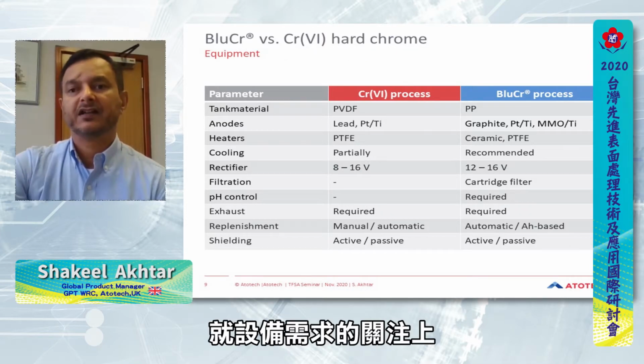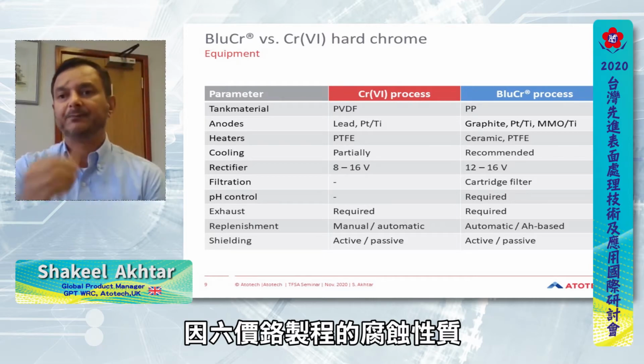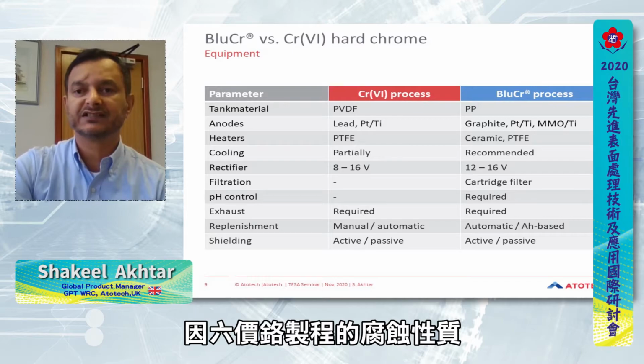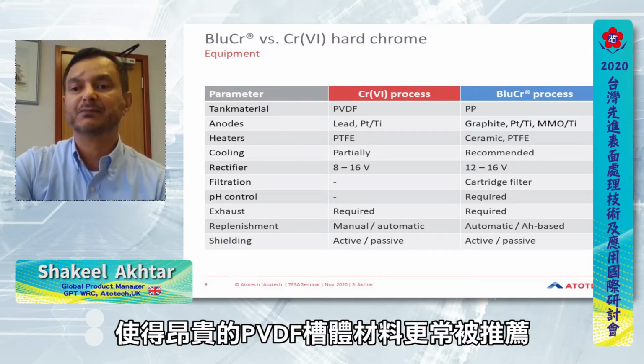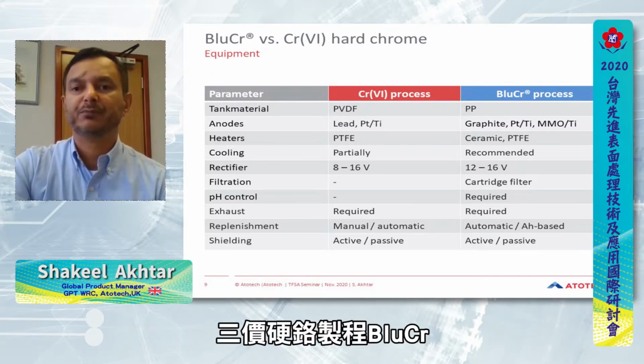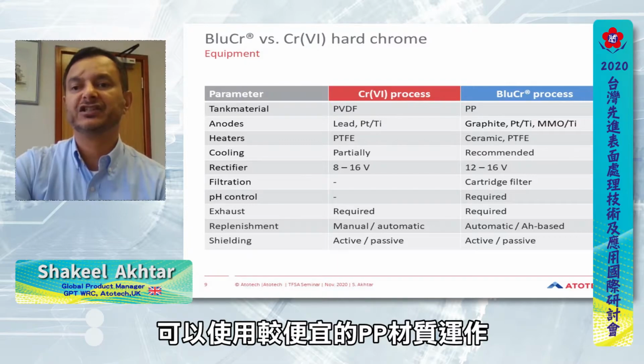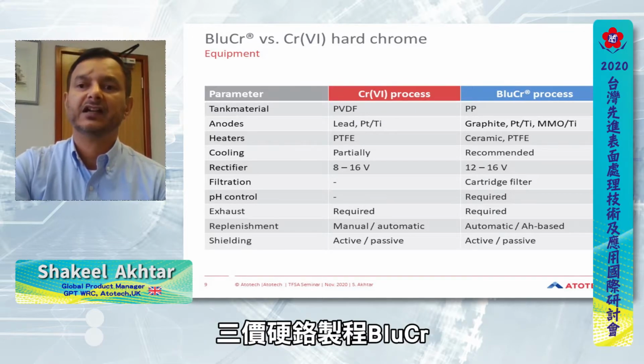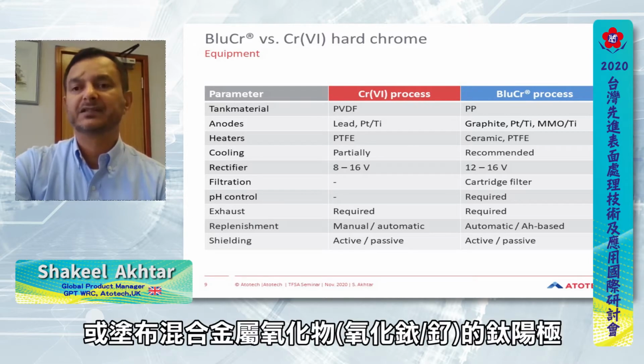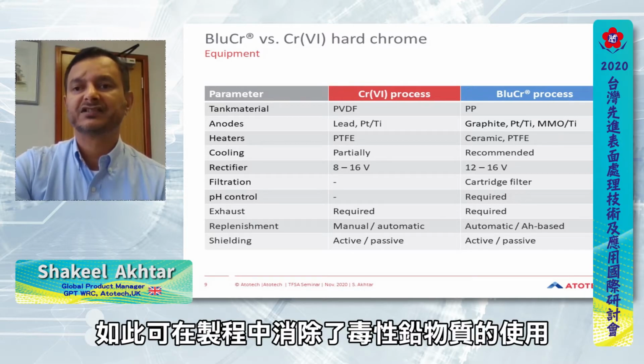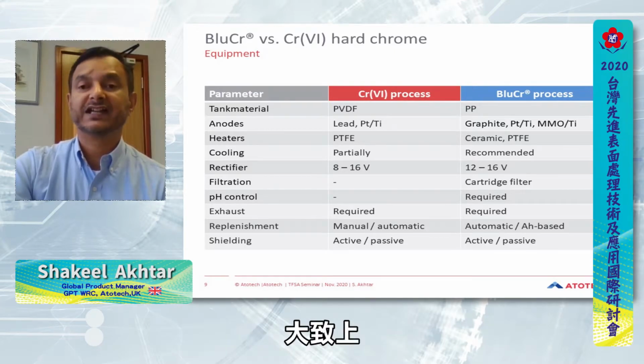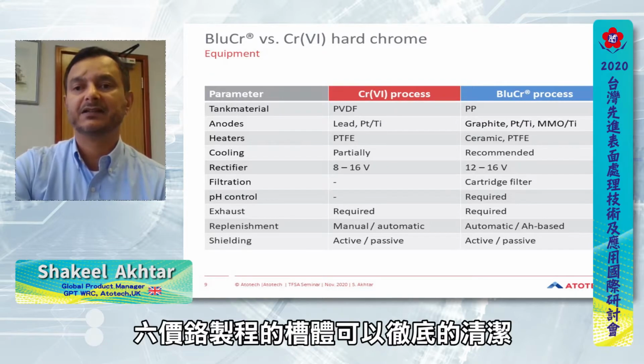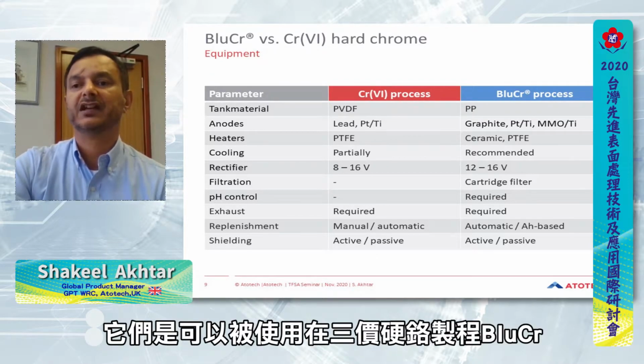As far as equipment requirements are concerned, due to the corrosive nature of hexavalent chrome processes, expensive PVDF tank material is usually recommended. However, the blue chrome process can be operated in tanks constructed from cheaper polypropylene materials. Blue chrome can be operated with graphite, platinized titanium, or mixed metal oxide on titanium anodes. Thus, the elimination of toxic lead from the process with blue chrome. All other equipment requirements are the same. In most cases, the existing hexavalent tanks can be cleansed thoroughly and used with the blue chrome process.